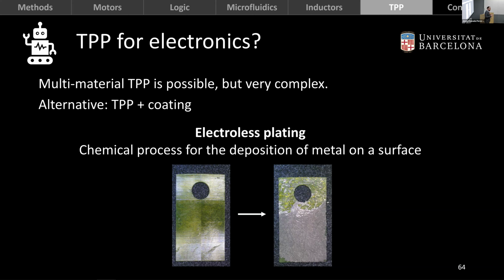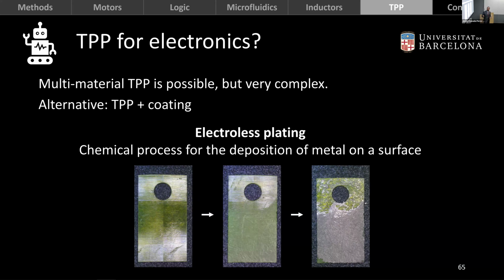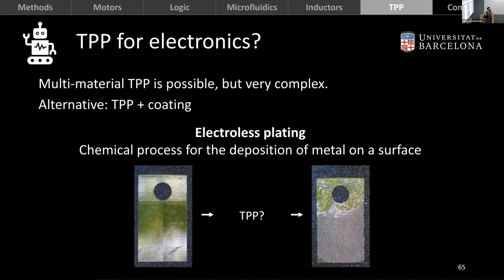Now, usually there is an intermediate step that is basically a surface conditioning operation. In this case, for example, we simply sandpaper the sample to give it some roughness. It can also be done chemically. There's other possible processes. And what we wondered was, can we substitute that step with two-photon polymerization? Because if what we need is certain surface roughness, then thanks to the resolution of TPP, we can actually just print that roughness on the part.